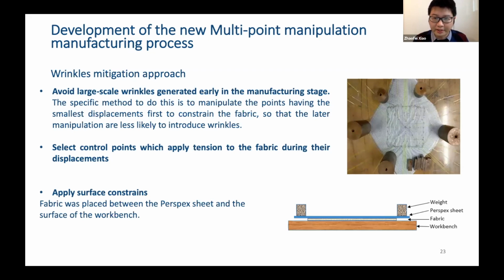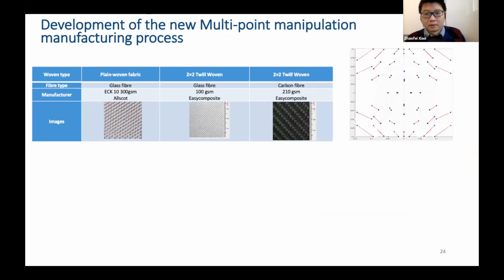So during the manipulation, we place the fabric between the perspex sheet and the surface of the workbench. So we apply some surface tension to eliminate the wrinkles. Then we select 3 different types of fabrics: 2 glass fabrics and 1 carbon fabric, and we redesign and reselect all the control points to make sure that in all the manipulations, all the nodes will apply tension to the fabric.